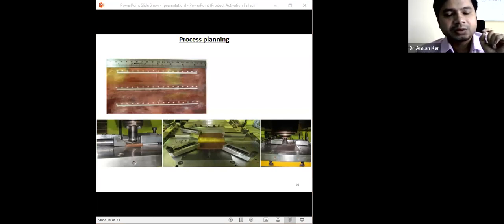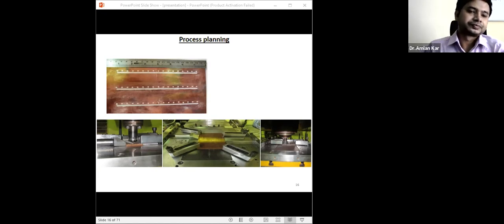Okay, so ceramic particle hardness is very high, but the hardness of the polymer particle, which has been obtained in this process, is not substantial. So therefore, you can overcome that wear of the tooling, and therefore we can obtain a homogeneous property of the composite which has been fabricated. So there are different steps. The first step is this one, and therefore you process it, and after processing you pyrolyze.